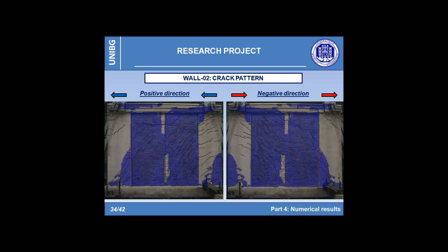Here it is possible to see the differences regarding the damaged area at the base of the shear walls. The first appears mainly cracked due to the bending moment contribution, showing cracks with regular spacing arising horizontally from the outer edge of the wall and tending to develop downwards thanks to the contribution of the shear action. In the second wall, instead, it can be seen how at the base the cracked area is extending more in height due to the presence of an inclined strut. In fact, you can see how the cracks have an oblique orientation and follow the principal compressive stress trajectories.